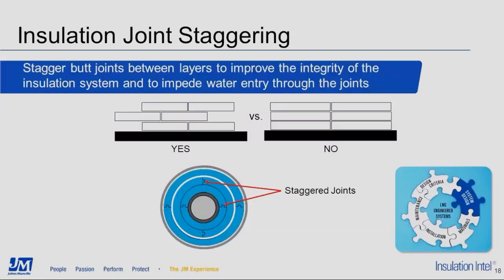The bottom picture shows the recommended staggering design for the longitudinal joints. The longitudinal joints in each layer should be staggered by about 90 degrees from the joints in the adjacent layers. As with the butt joints, staggering the longitudinal joints in this manner makes a more tortuous path for water entry. In addition, the joints in the outermost layer should be located about the 3 o'clock and 9 o'clock positions on the pipe. Forces exerted on the pipe are most likely to occur at the top and bottom, the 12 and 6 o'clock positions. So it's best to locate the joints at places where these forces will not be exerted, which would be at the 3 and 9 o'clock positions in the outer layer.